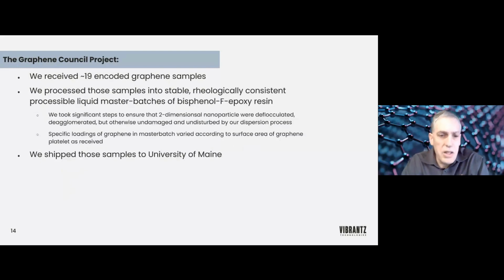So in the early onset of this project, we received 19 encoded samples. We didn't know what they were. One thing I can tell you about the graphene samples we received, they were unidentified. They had the code numbers on them identifying different materials, and they differed widely. There were some samples that seemed to have surface area, to our inspection, of maybe a neighborhood of 100 square meters per gram. There were other samples that appeared to have surface areas much higher, possibly even above 1,500 square meters per gram.